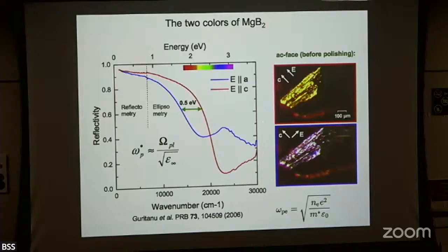This is the reflectivity as a function of frequency. This edge, that's the plasma frequency. So that's a characteristic shape for a metal. The reflectivity is very high, in an ideal metal close to 1. And then where the dielectric constant goes through 0, from negative to positive, you get this steep drop. And then something else happens at the higher frequency.